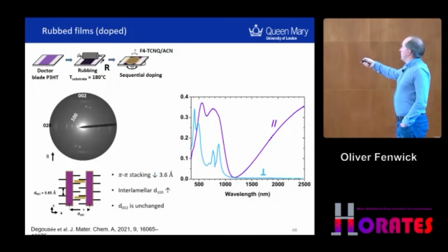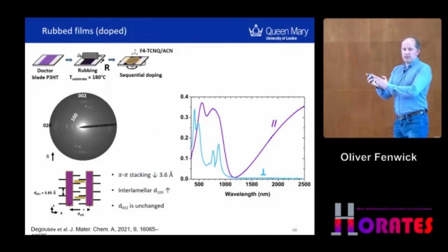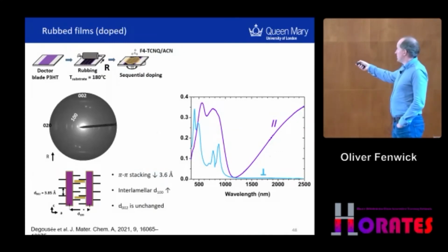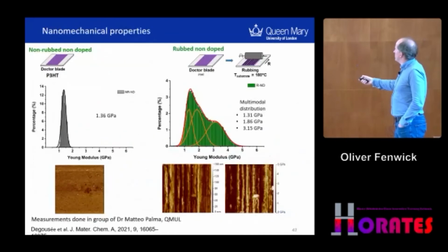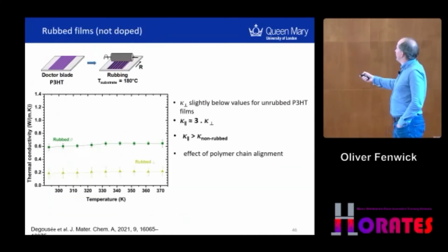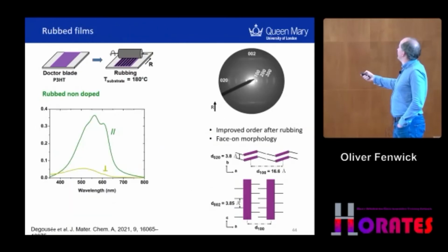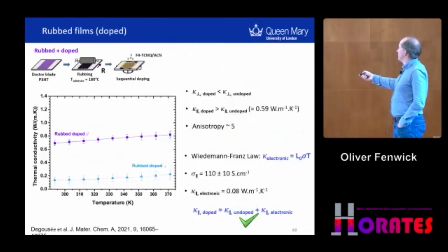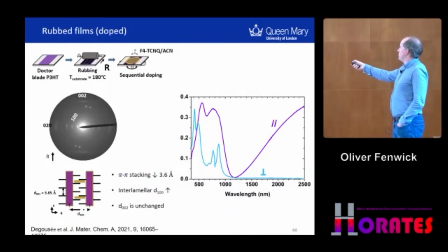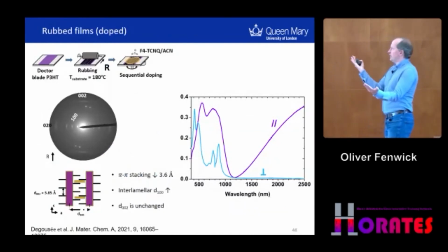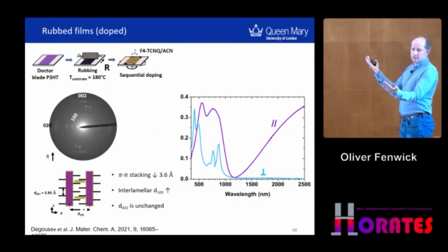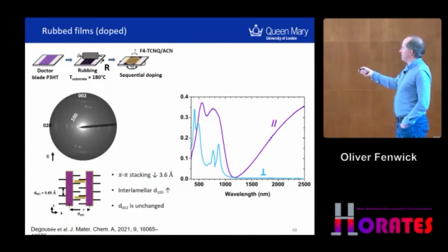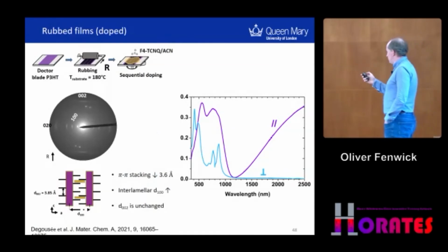What else do we see? From this structure, we see a slight decrease in the pi stacking. Let me get my numbers right. There we go, 3.6. So it has decreased a bit. There is a decrease in the pi stacking and an increase in the interlamellar distance when doping. So you'd think that in the pi stacking direction, that might be favorable for thermal transport. In the interlamellar stacking direction, that may not favor transport.